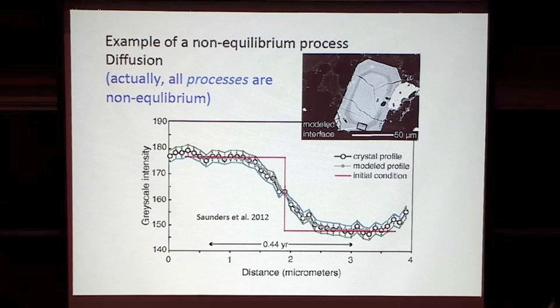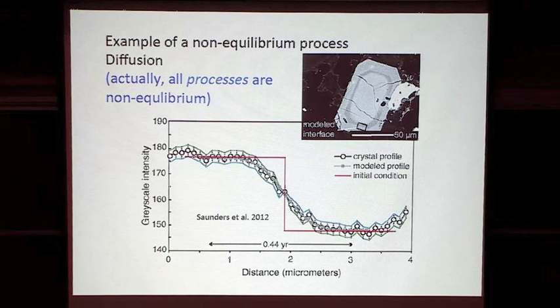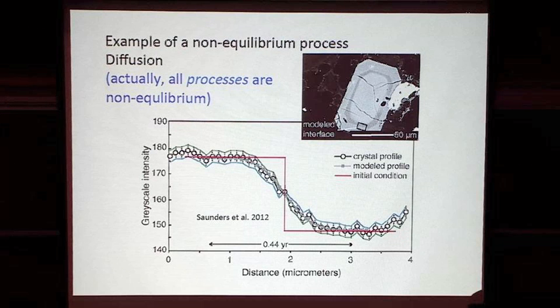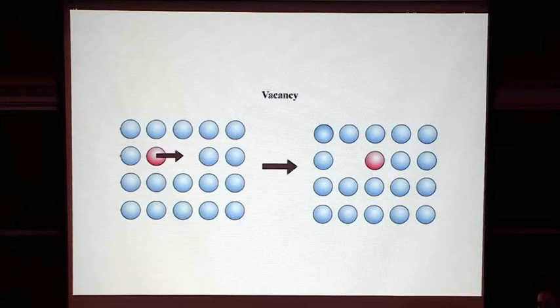But when we actually see the diffusion, and I should say this is a diffusion of iron in this profile, what's actually going on at a microscopic scale is a lot more interesting, or potentially a lot more interesting, than you would just calculate from, say, Fick's law. That's because in real materials, particularly in real crystals, diffusion of elements is coupled to a whole bunch of structural features in the materials that determine the diffusivity.